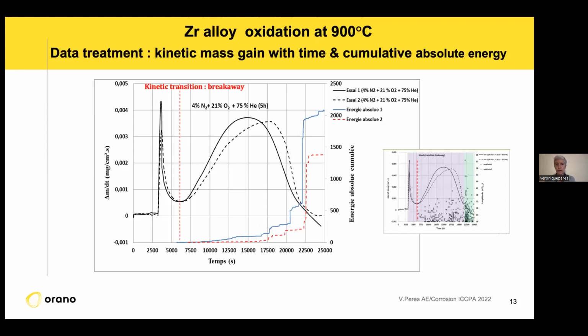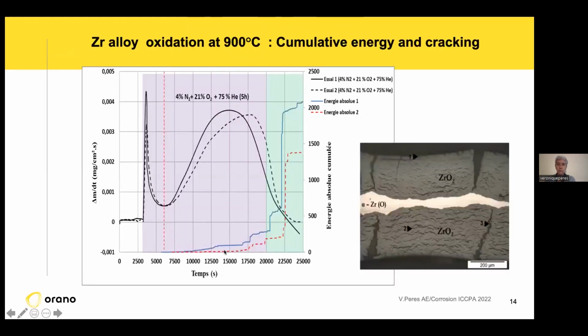After that, we have to attribute the cracks, and we look again at the pictures of the corroded samples, and we can attribute some cracks due to the cooling and some cracks due to the corrosion. So it's very interesting to have these pictures, and we use them. It will be useful to study the corrosion of zirconium alloy with these systems.